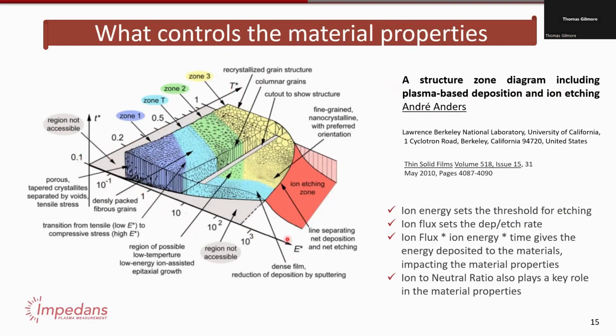But the axis I'm more interested in is this one here with energy labeled. Energy delivered is pretty much to do with the ion energy and the ion flux over time, so you can see time on this axis. And the higher the combination, at some point, when ions are above a certain level, this is material dependent of course, above a certain energy they start etching instead of depositing. Below that energy, they can etch a little bit, so you don't get the same thickness as you would. It's not net deposition. And then when the energy is low enough, you get more deposition. So just keep in mind that the ion energy and the ion flux matter, as well as the temperature, not just for how quickly or how slowly a material forms, but what material forms, like the difference between amorphous and crystalline silicon.